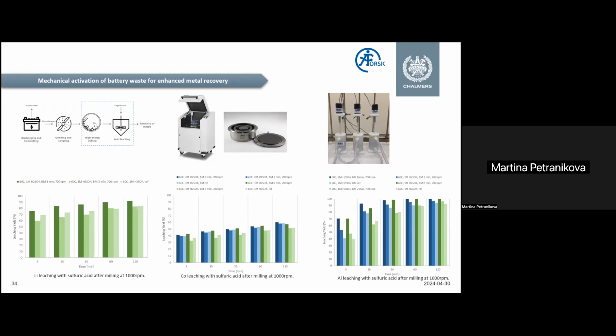And what we could see when we were testing the base conditions was that for the lithium and for the cobalt, the increase of the leaching efficiency was from 5 to 10%, which is not much, and it cannot compensate for the energy need for this kind of milling. But for aluminium, it was also quite important, or a little bit increased, so that can be good and improve the removal of the impurities. Maybe this doesn't look very significant now, but in case of need for even increased efficiencies in the recycling process, this could be one of the steps where the recycling efficiencies could be improved for the material recovery.